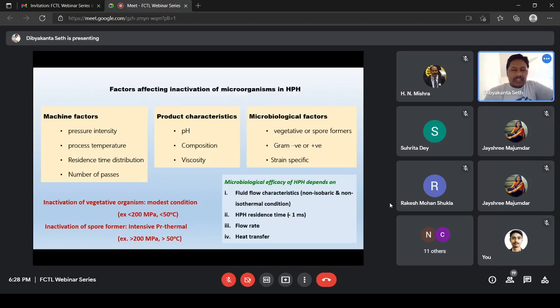Some strains may not be properly affected by high pressure, or high pressure may not be effective to a particular strain. But with the same species, another strain will give a good result. So it has been found that inactivation of the vegetative organism can be achieved with modest conditions, like less than 200 megapascal with less than 50 degrees Celsius. That means non-thermally we can achieve the killing of the vegetative organism.